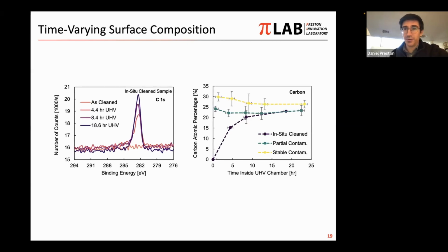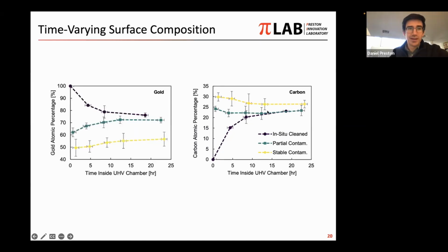Conversely, we said we had these other two samples, one of which is partially contaminated, and the other is fully or stably contaminated. And I mentioned that those actually experience desorption of contaminants in this ultra-high vacuum environment. And so this effect is almost omnipresent unless you happen to start at this equilibrium level by luck. And this is a result that is measured converse to the gold concentration on the surface. As we might expect, we're covering up gold sites with carbon during contamination, or vice versa. If we're desorbing contaminants from the surface, we're seeing more gold.